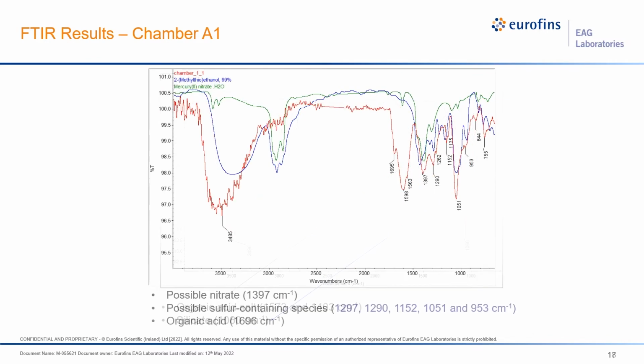Another spectrum, again, this is all from the same exact sample, from the same chamber. We see a sulfur-containing species, that's in the blue. We see a nitrate, that's in the green. And also the 1695, that's an organic acid. So we see an organic acid salt. That's telling us about some pretty significant contamination of that chamber. And as we go through the results, you'll see that chamber A1 was kind of the worst.